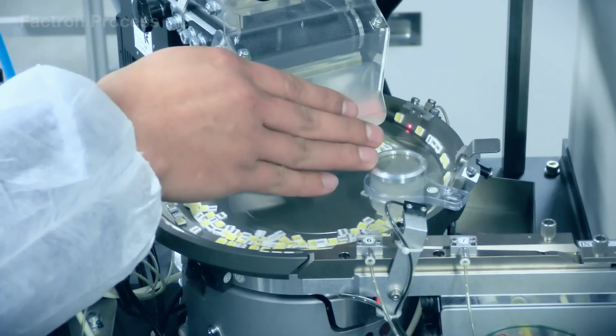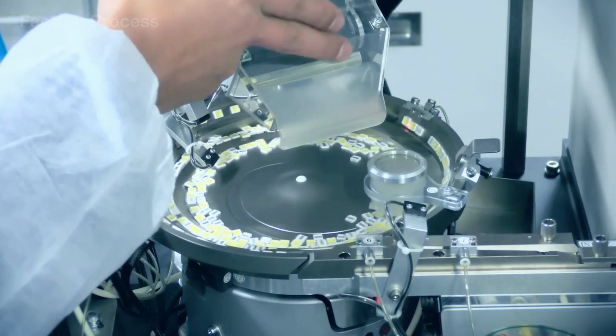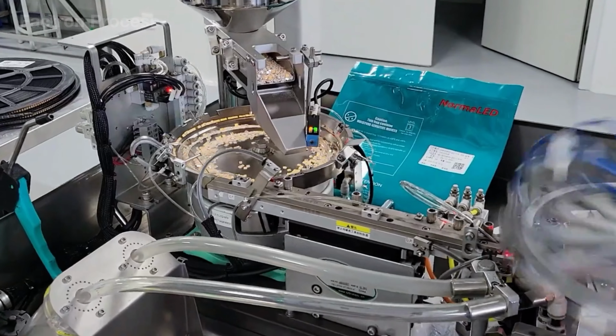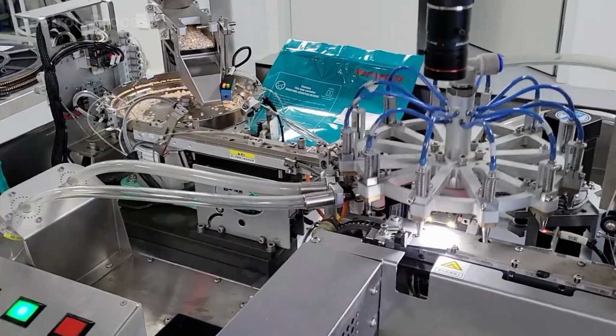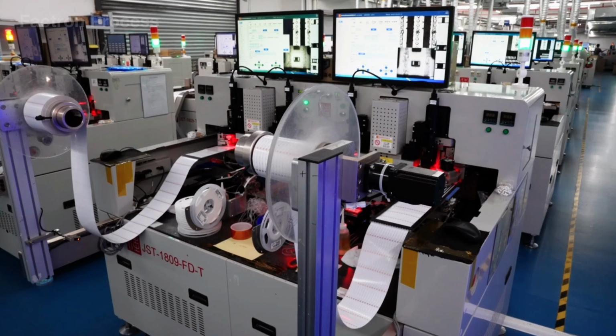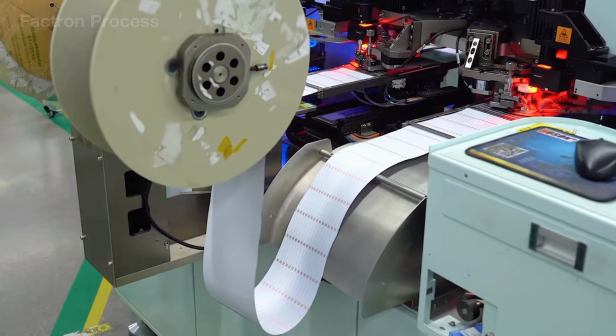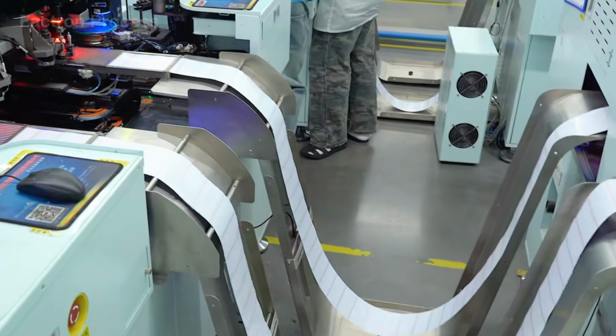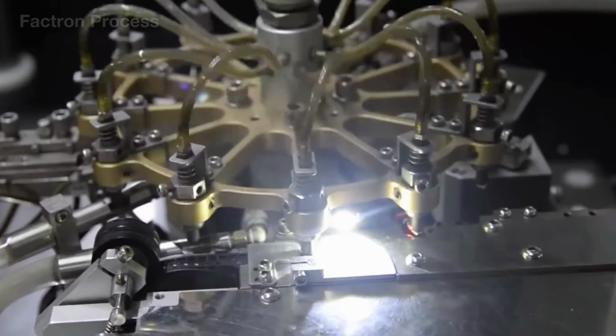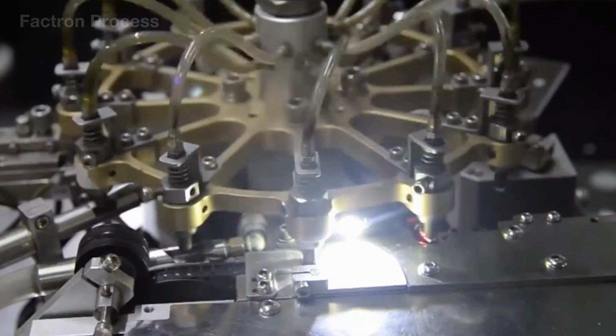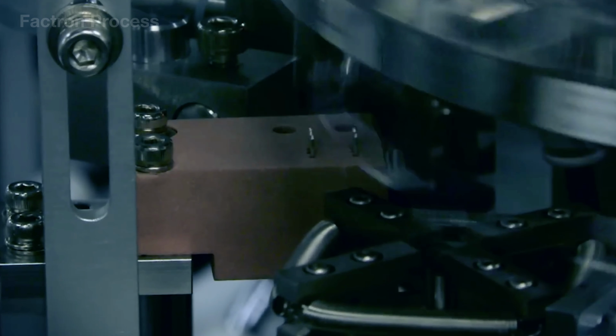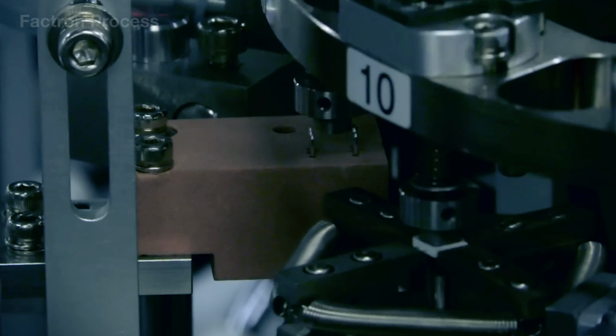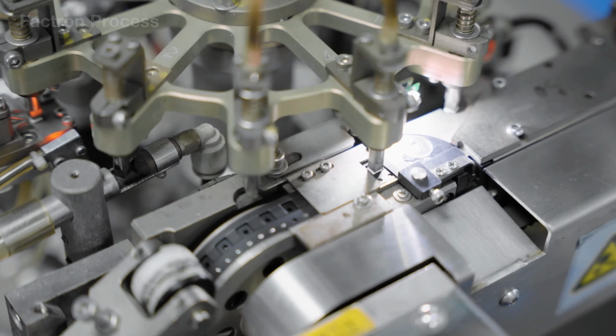Once the phosphor layer is complete, the SMD LEDs are transferred to the SMT production line for mounting onto the flexible circuit strip. First, the FPCB roll passes through a solder paste printer, where a thin steel stencil helps deposit a nearly identical amount of material onto each copper pad. The paste temporarily holds the components in place and later forms the electrical connections during heating.